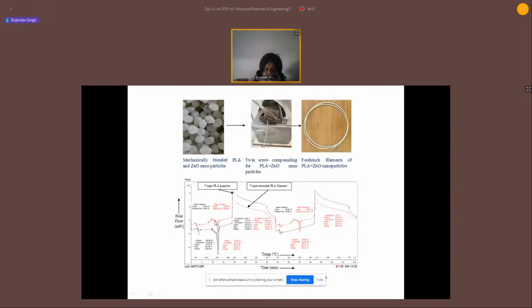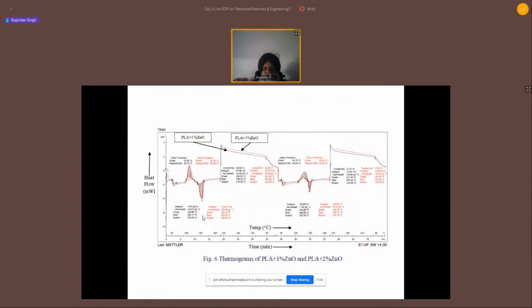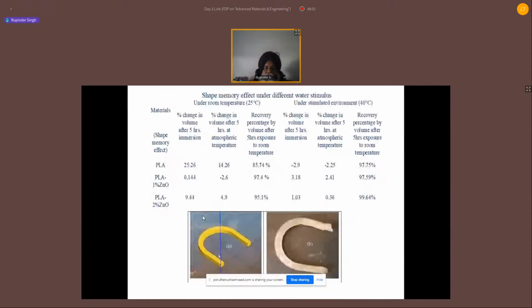That feedstock filament was processed for different thermal properties. So I can see what the thermal property is without reinforcement, then with different levels of reinforcement, 1%, 2%, 5%, and what the effect is on thermal stability, whether it is improving, so we can check it. One important thing we did over here, we made some U-shape component, and then we tried to see the effect of the stimulus as water and temperature.